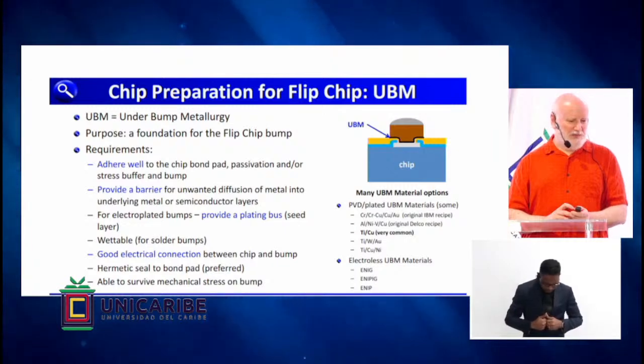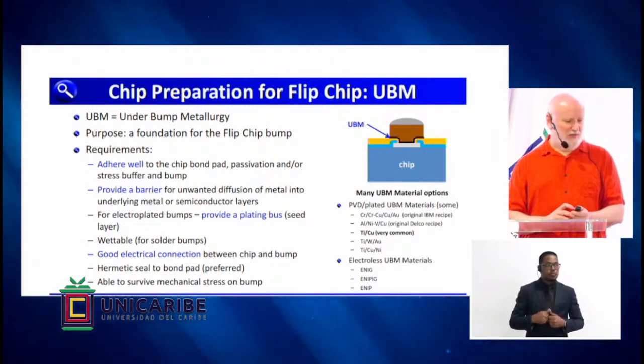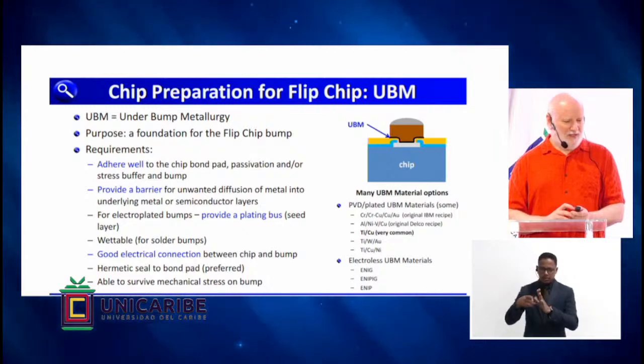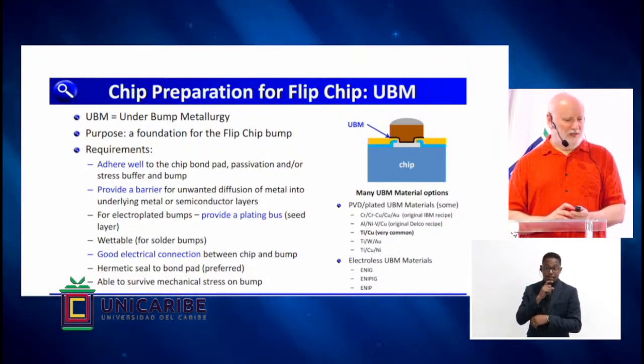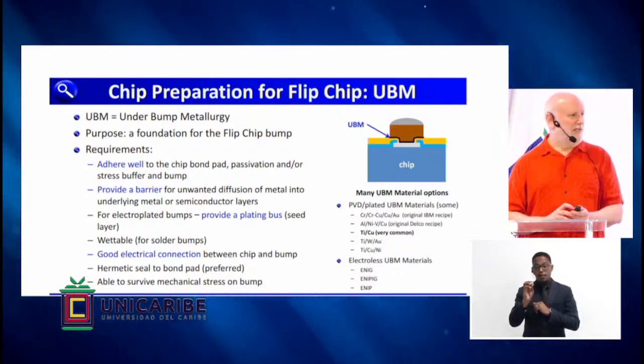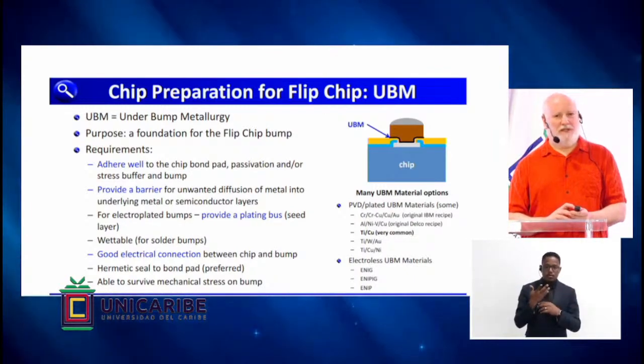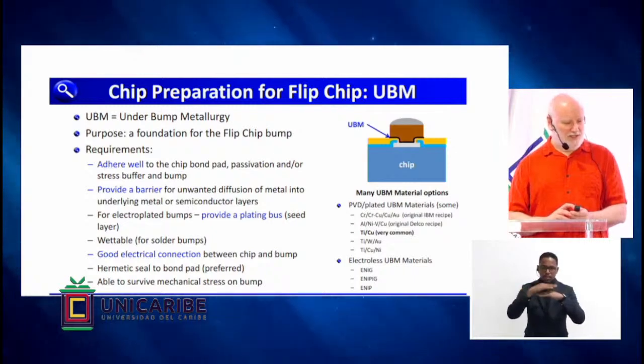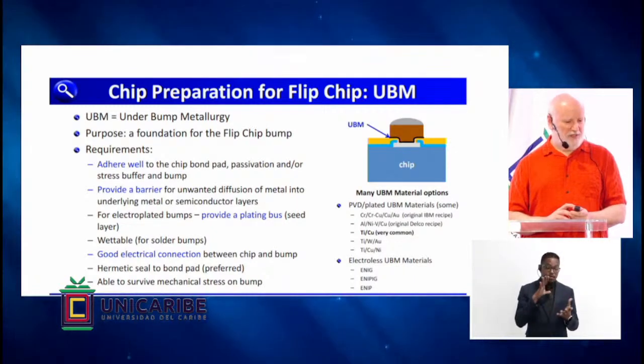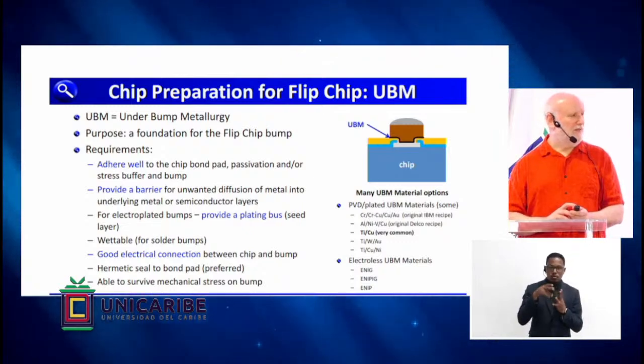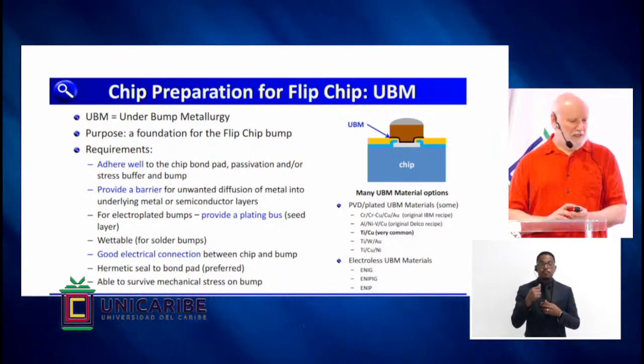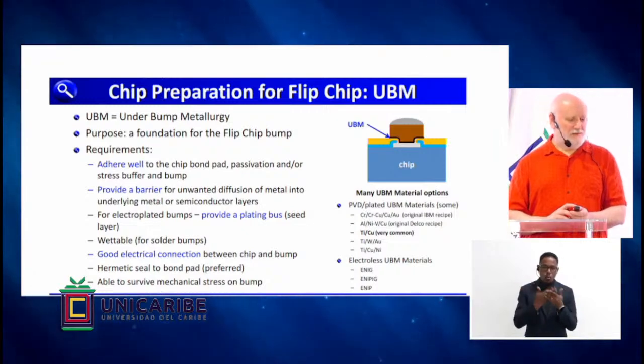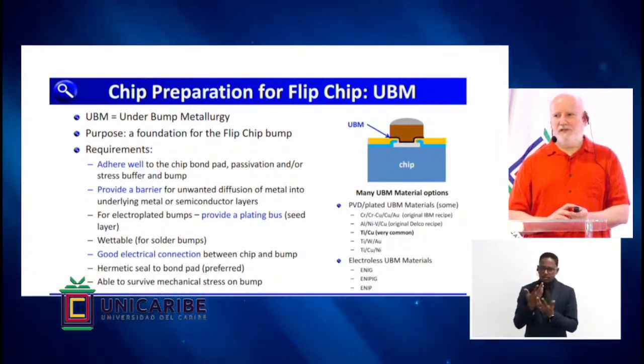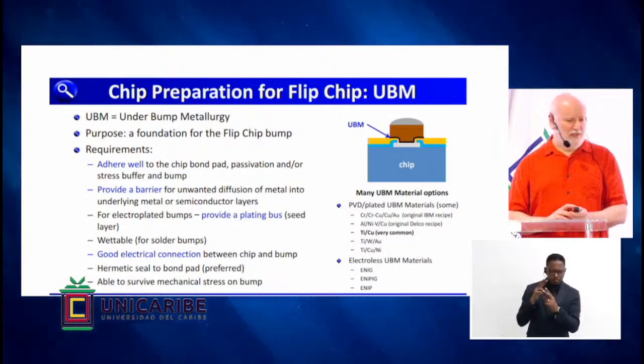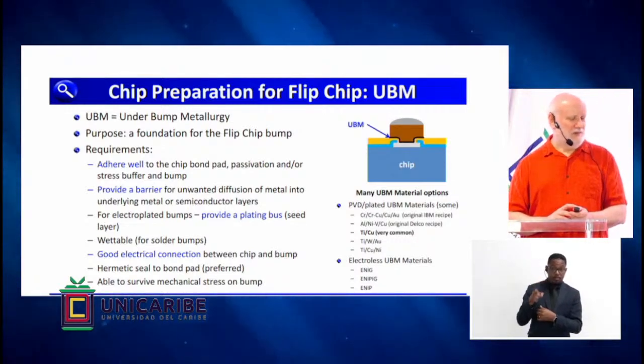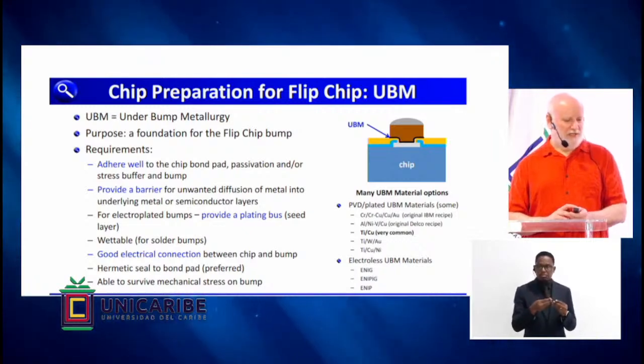So it turns out the UBM is quite important, and it has a lot of different requirements on it. That UBM has to adhere well. It has to provide a barrier. You don't want certain metals to diffuse into the silicon device. For electroplated bumps, it provides a plating bus. Has to obviously have good electrical connection. So there's many different flavors of this that people have tried over time, but pretty much in the industry now, at least for copper bumps, it's resolved into a pretty simple structure of a titanium layer and a copper layer.